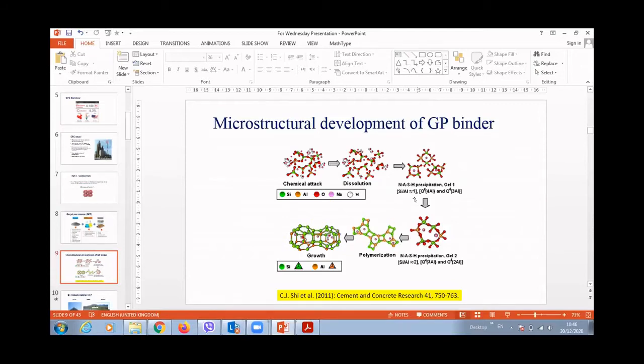So what's the main mechanism in geopolymer or alkali activated materials? It's mainly based on how the chemical solution we use reacts with the binder. For example, if we use an alkaline solution based on sodium silicate and sodium hydroxide, that solution will dissociate the material, for example fly ash or slags, and that dissolution produces more ions and cations. Those ions and cations react together to produce a form of gel, which we call the gelation phase. That gelation phase, with more rearrangement and orientation, builds new bonding and new links to form the growth or polymerization process, then the hardening process.